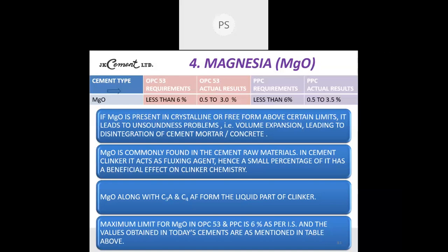If MgO is present in crystalline or free form above certain limits, it leads to unsoundness problems, that is volume expansion, leading to disintegration of cement mortar and concrete. MgO is commonly found in cement raw materials. In cement clinker, it acts as a fluxing agent. Hence, a small percentage of it has a beneficial effect on clinker chemistry.